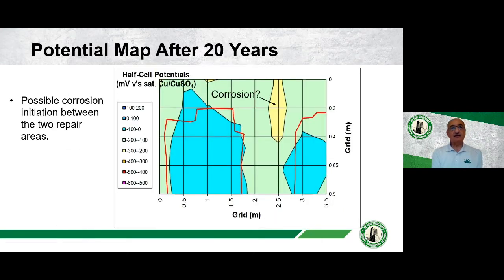Okay, so again, going back to the 20-year results, we did a potential map. We did that every time we took some measurements. We did a potential map of the whole area. And at 20 years, we could see that there was an area where corrosion might have been occurring. You can see that within the patch repairs themselves, the potentials are very, very noble. There's obviously no corrosion there, or not very much corrosion. Again, the potentials are noble, and the steel is passive. But there's a question mark around this area here between the two adjacent repairs.